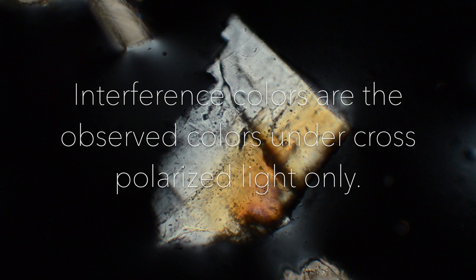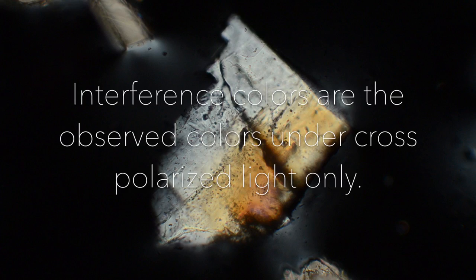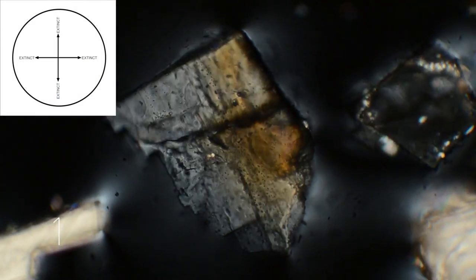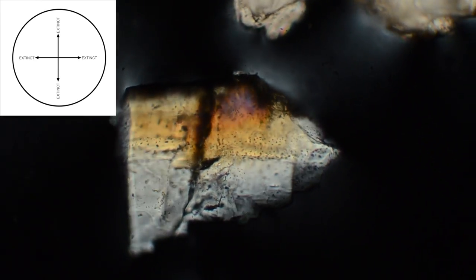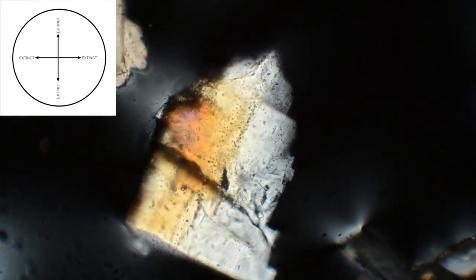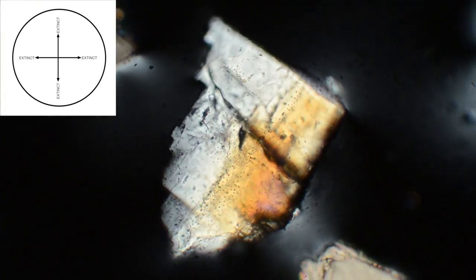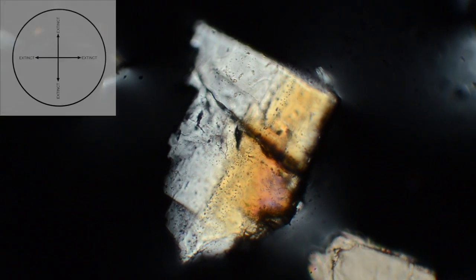The colors that you see now are known as interference colors. Interference colors are the observed colors under cross polarized light only. In cross polarized light, notice that as I rotate the stage a full 360 degrees, the interference colors fade to black exactly 4 times. These are known as extinction positions and occur 90 degrees away from one another.